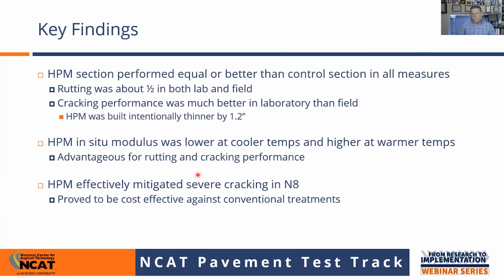So some of the key findings, just to summarize, what we found in that first experiment was that the high polymer section had equal or better performance than the control in all measures. The rutting was about half or less than half in both the lab and the field. The cracking performance was much better in the laboratory than the field, but in the field, remember that we built it thinner. And so we were trying to get it to where we would see maybe equivalent or a little bit better performance.